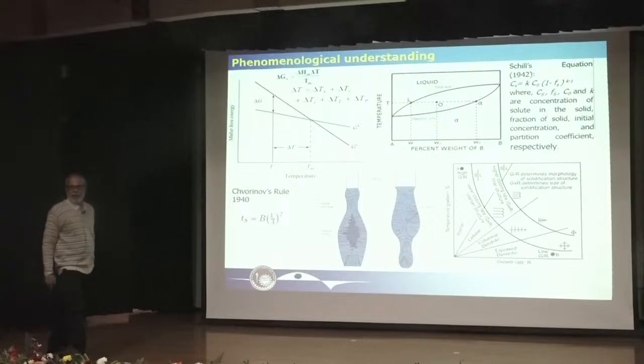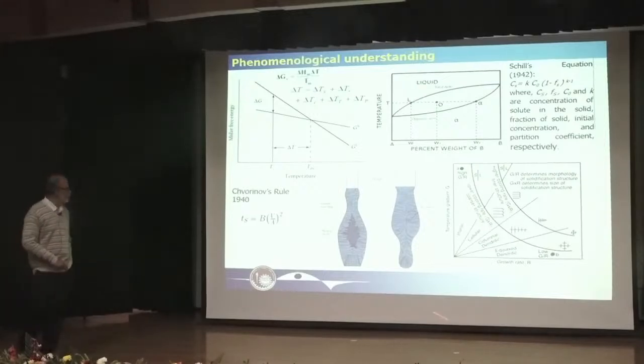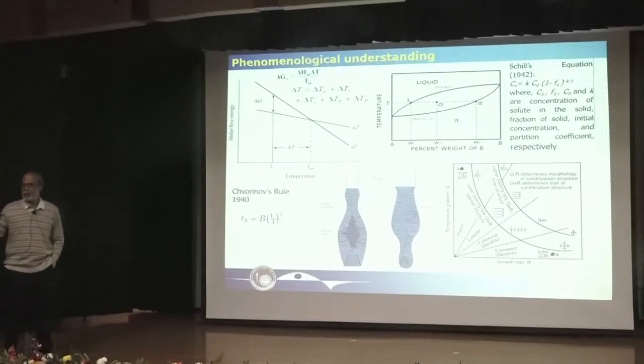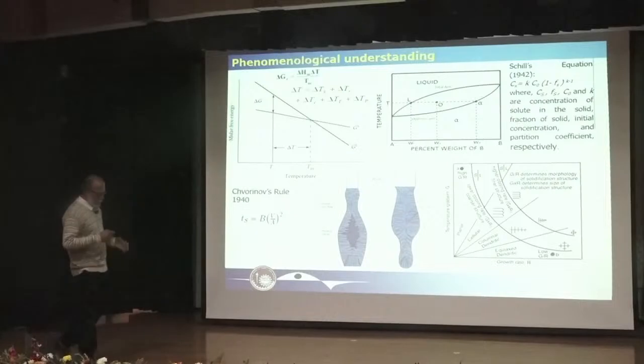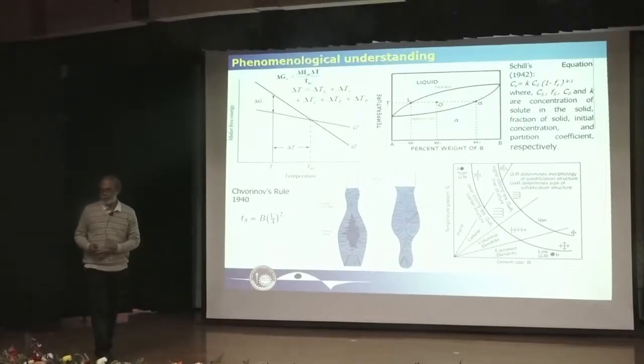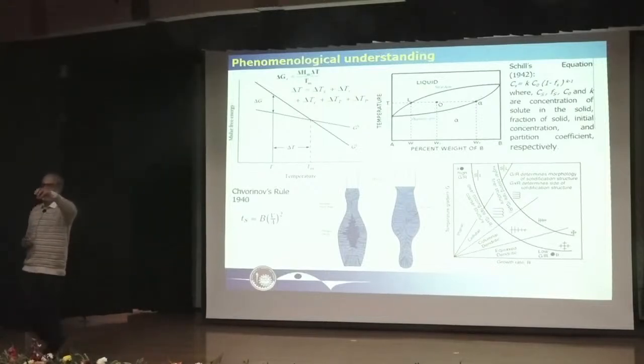And for industry, one breakthrough happened in assessment of shrinkage and eliminating shrinkage, which was proposed by Chvorinov, is absolutely empirical. Simply, the time of solidification is basically the ratio of volume and surface area of a particular component for a given shape. It is like this: when most of the metals solidify, there is a volume shrinkage, and we need some external feeder to compensate the shrinkage in volume. Now, suppose this is the location of the external feeder, and if there is a choke which has lower volume to surface area, that hinders the liquid from flowing to the shrinkage, right?